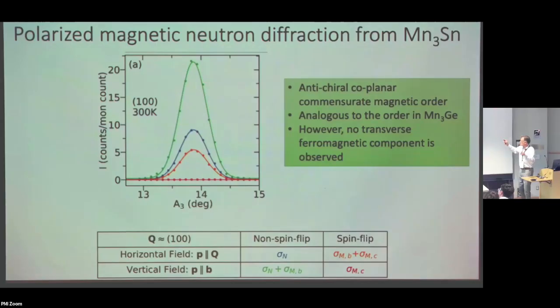That's fine. But there's one more point I should mention, which is this channel is very, very helpful, even though there's no intensity at all to be seen. That channel is only sensitive to the magnetization which is along the c-axis, so normal to the Kagome planes. But we see absolutely nothing there. So that shows us that this really is a planar structure. The spins are really in the plane. So this is really just categorical information that comes out from this kind of experiment. That's why we like it.